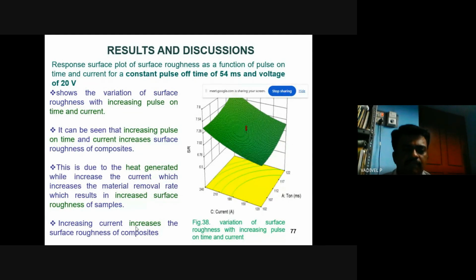Here is the variation of the surface roughness with increasing pulse on time and current. It can be seen that with the increase of the current, the surface roughness increases due to the heat generated while increasing the current. Because of this current, the metal removal rate increases along with the surface roughness. The increase in current increases the surface roughness of the composite material.